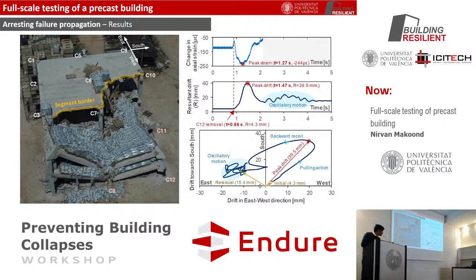As in the initial phases, as column C12 was removed, just after the sudden removal, the whole structure was moving in this direction, southwest in this case, according to this compass. It kept on moving in that direction, but shortly after the failure of the connection around C7, there is a backward recoil, which shows a tugging effect, and then the movement of the remaining part of the structure went into an attenuating oscillatory motion until it stabilized with a notable residual drift.